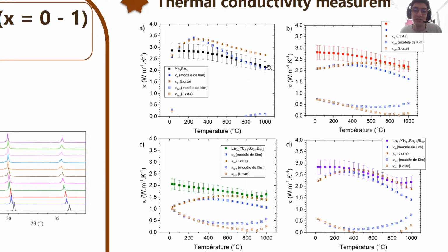The total conductivity was estimated using the Dulong-Petit law for the estimation of the specific heat. And actually, for this material, we have an example where it does not work properly, as the Dulong-Petit law does not give an acceptable estimation of the specific heat, since it is taken as constant with temperature, which is not the case in reality. So the next work that I have to do is to perform a measurement of the specific heat for this material and get back to the total thermal conductivity to give a better estimation.